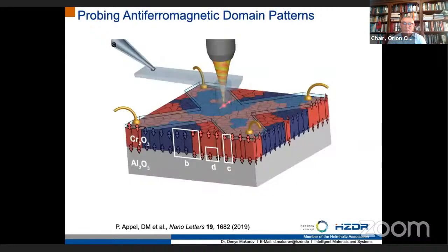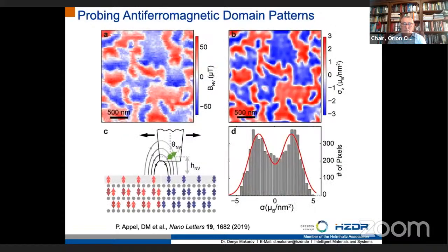To answer these questions, we established a very fruitful collaboration with a group of Patrick Maletinsky at the University of Basel. They are experts in scanning nitrogen vacancy magnetometry, or NV microscopy, which they successfully applied to study antiferromagnetic materials. In essence, the technique allows you to measure the magnetic stray field and magnetic stray field distributions over the surface of the sample. The blue and red contrast is a real space imaging of antiferromagnetic domains.